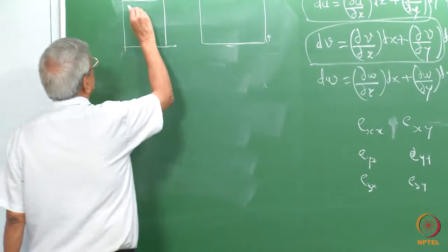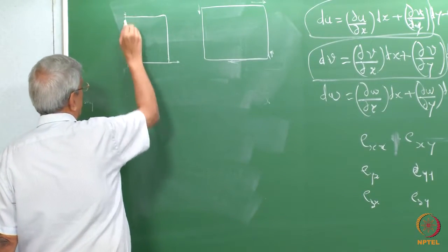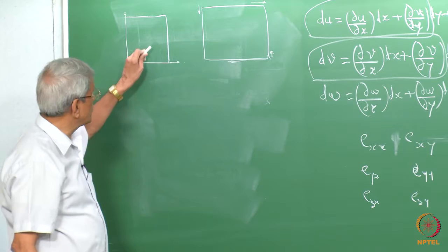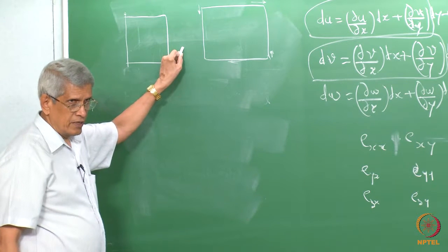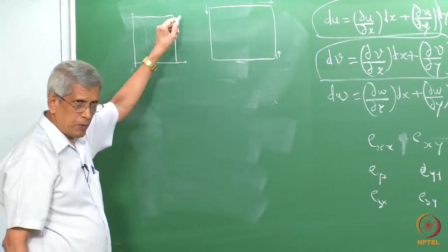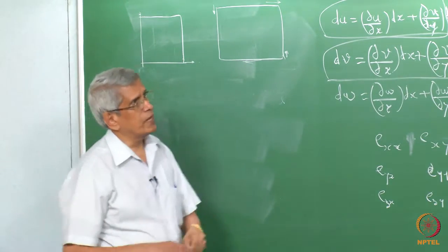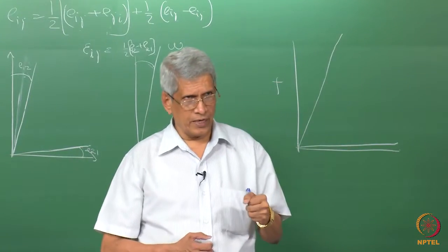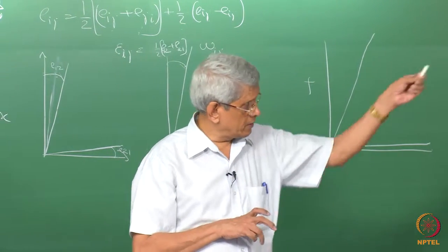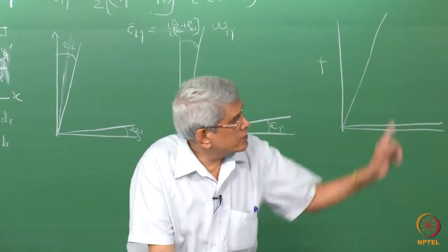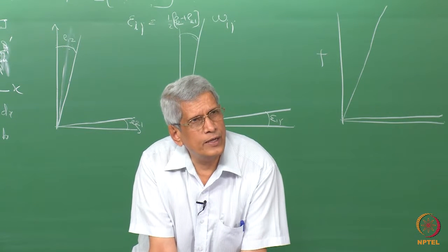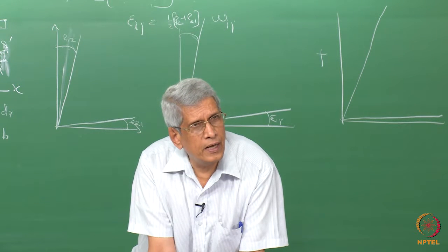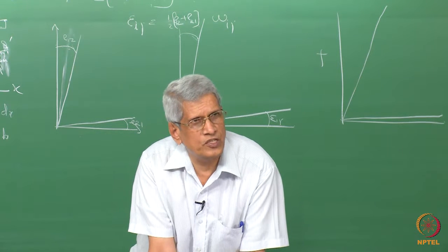This is the axes, or the coordinates, which we have chosen to represent the sample. With respect to this, we can choose another coordinate system, inclined with respect to it but perpendicular to each other, to which we can apply some strain, elongation in one direction and compression in the perpendicular direction. The same shape change could be achieved. This shape change is essentially equivalent to giving just pure strain but no shear strain.